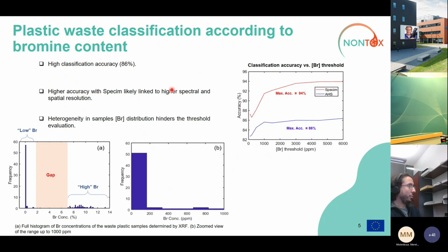So here are some results that we got for the classification, and I will begin actually with the lower part here, where we have these histograms obtained from the XRF, where we can see the concentration distribution in the plastics. So one thing we noticed was this gap in concentration, which then guided us to the approach of classification. We noticed the plastic was mostly either very high bromine concentration, so this is in percentage, or very low. So we then proceeded to develop a machine learning classifier so that we can use the spectral information to classify according to some concentration thresholds.